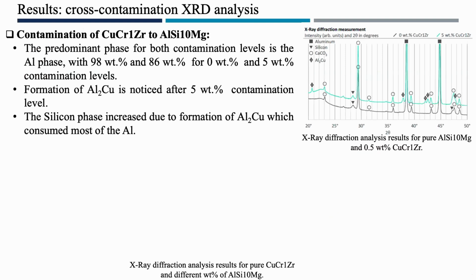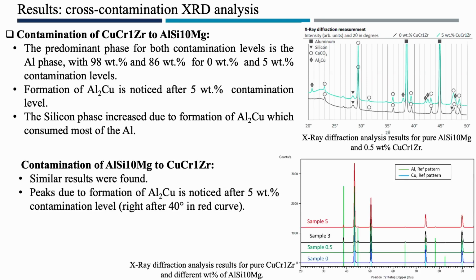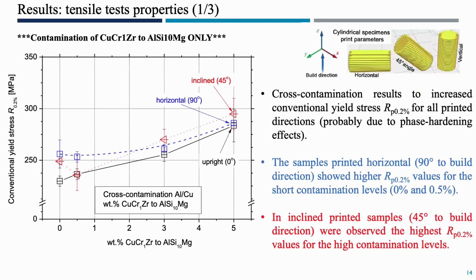So now here we have two different cases. The contamination of copper to aluminum. For example, here you can see that for the 0.5% copper contamination, you have the peaks showing aluminum and copper, and for the contamination of aluminum to copper, we found some similar results with different peaks. As I told you, still it's a preliminary work. Unfortunately, we didn't finish the contamination or the tensile test of the contamination of aluminum to copper. That's why I'm going to present you only the contamination of copper to aluminum.